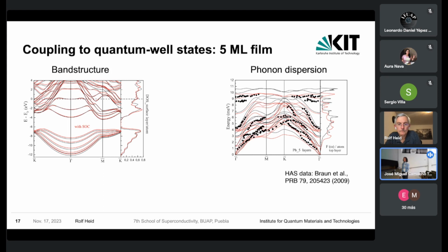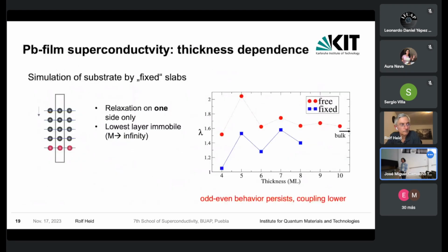When you explained that for the lead system, this system with several layers, in particular this one, you find out that you have to fix the first layer in order to be as close as possible to the experimental results. What could be the physical meaning of, by fixing this layer, why the electron-phonon coupling is reducing? Is it because you are breaking the symmetry of the, so to speak, axis of the layers, or you are confining some phonon modes, or what could be a simple explanation or reason why the electron-phonon coupling is decreasing?